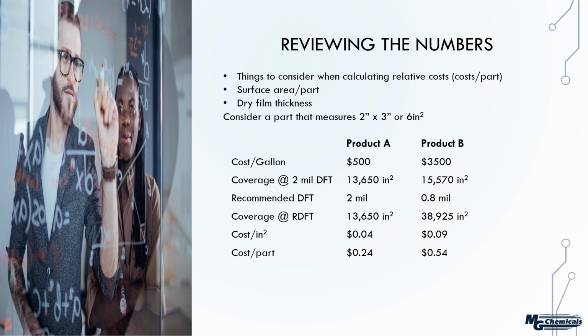So right off the bat, we can see that it's closing the gap somewhat in terms of the cost difference because it's slightly more efficient. You can cover a slightly bigger area at 15,570 square inches. But now let's take into account what the recommended dry film thickness is. And maybe this particular product you can apply at a much lower thickness. So in this example, instead of 2 mils, you have 0.8. So again, it's a fraction of product A, and that's going to narrow that gap as well.